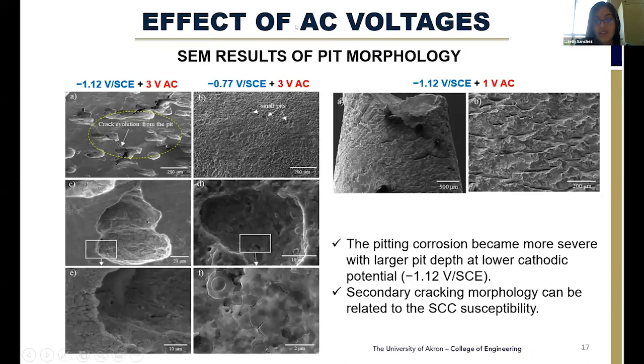In addition to that, I show you here the SEM study, but not of the fracture morphology, just the part outside the gauge section. We see how there are some pits that are bigger with the lowest cathodic potential. The microcracking is still present inside of these pits. And we found that some pits are connected through cracks. So we can see how cracking evolves. This is a crack evolution from the pit.